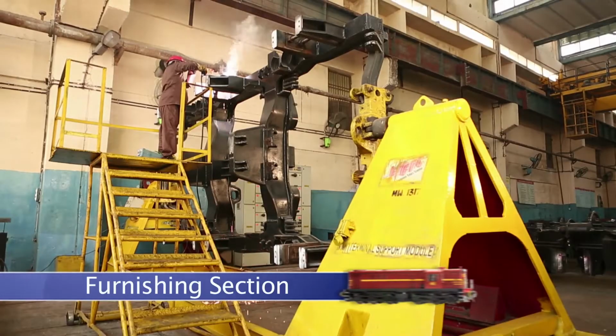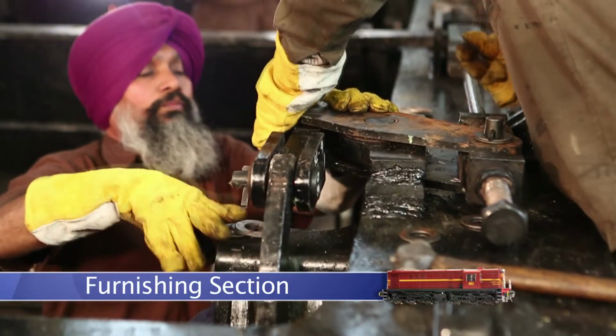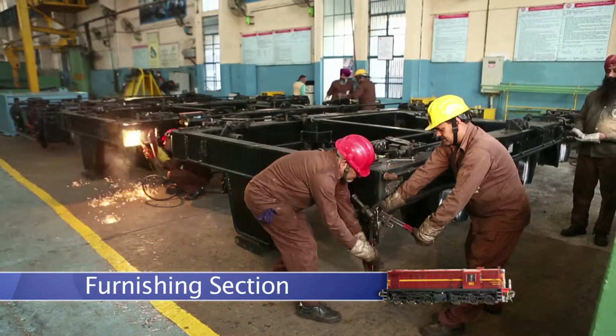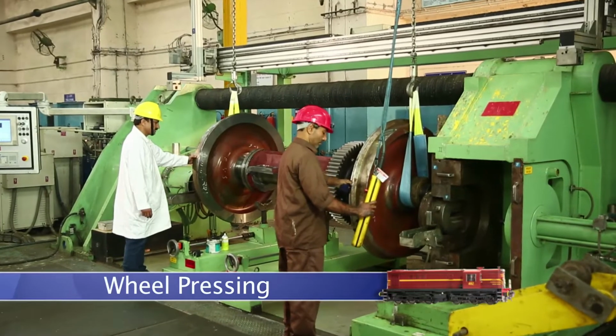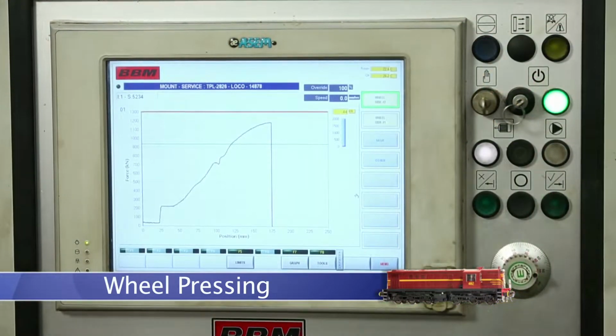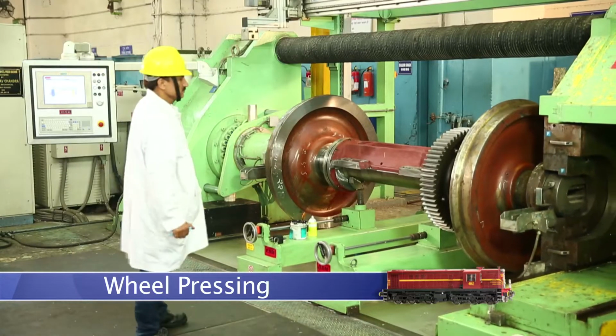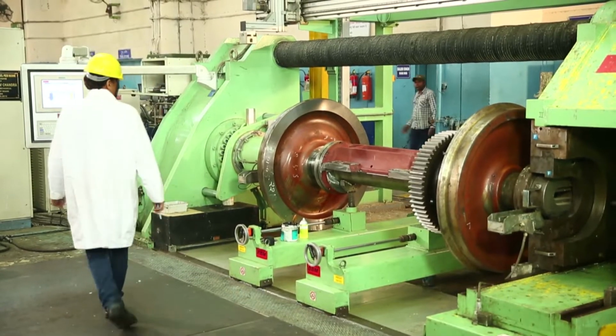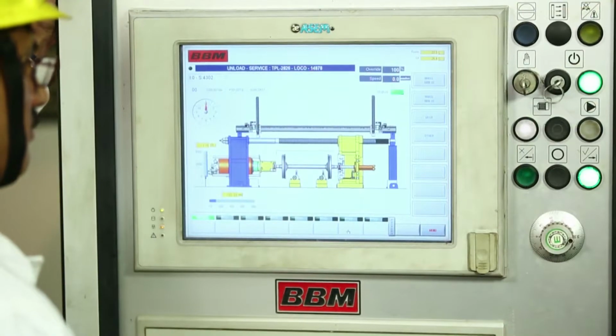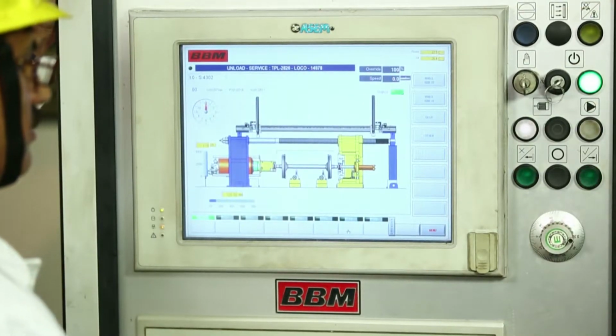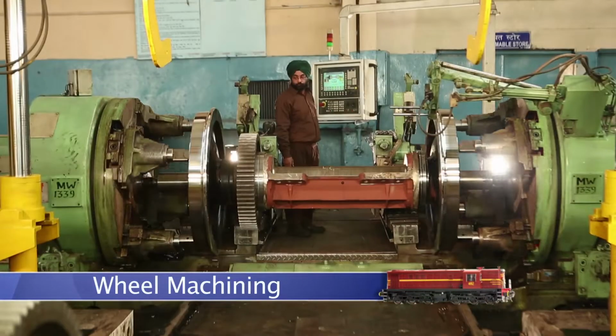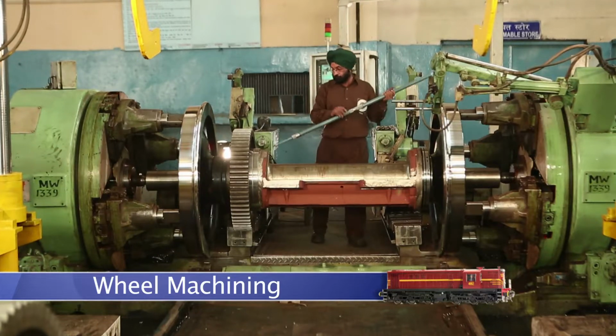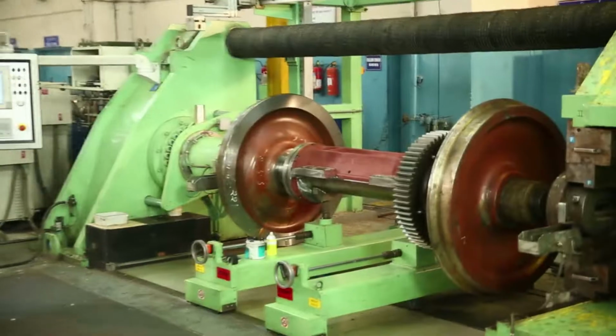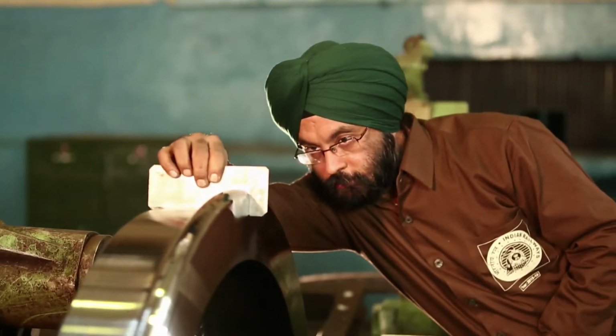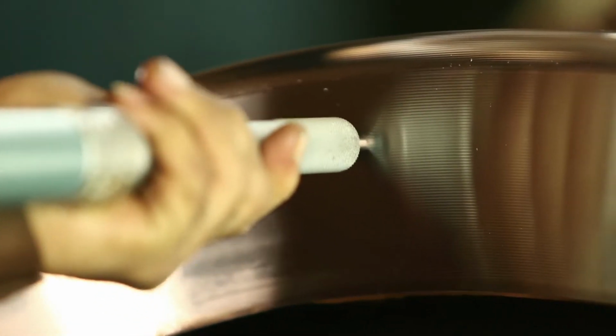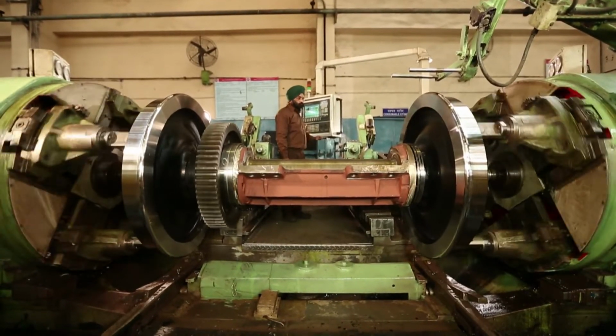Old serviceable or new unfurnished bogie frames are furnished in the frame furnishing section. All the brake rigging components and liners are assembled and welded here. Suspension tube and high-speed taper roller bearings are fitted on the axle, and then wheel discs are pressed at both ends on CNC wheel press machine at a pressure ranging from 95 tons to 132 tons. The data is recorded electronically for each axle. After wheel pressing, wheel disc profiling and line gauge, that is, distance between two wheel discs are maintained on CNC wheel profile machine. Tread diameter between 1092 to 1097 mm and line gauge 1599 plus minus 0.5 mm are maintained.